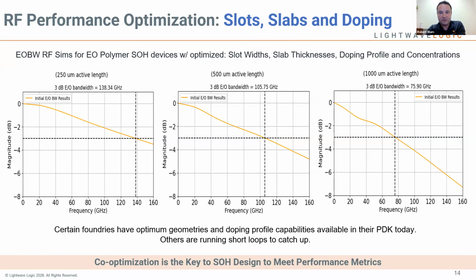So for these devices here on the right, for example, you have drive voltages that are less than 1 volt peak to peak or lower. So this is quite advantageous in terms of performance. Basically, you can get very compact modulators, sub-millimeter, with bandwidth above 100, 110 gigahertz or higher, as I showed here, with very low drive voltages. So I think this is all I wanted to talk about in my portion.